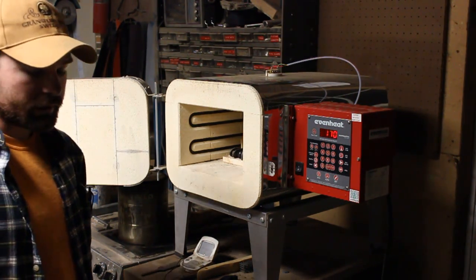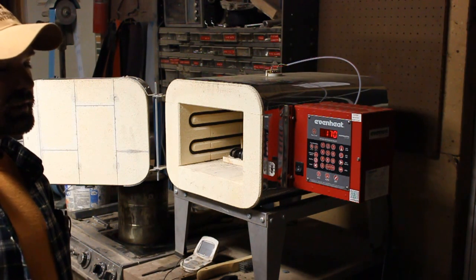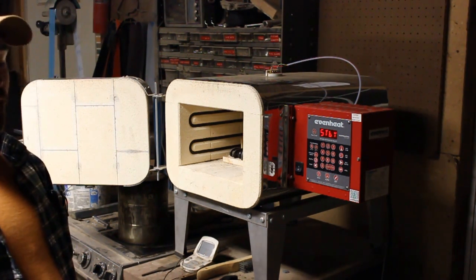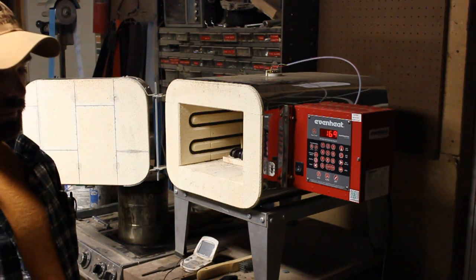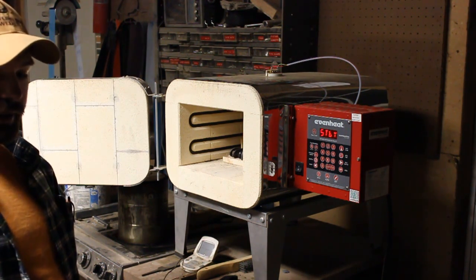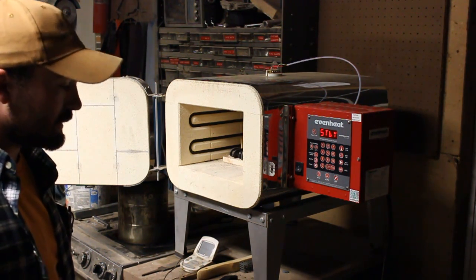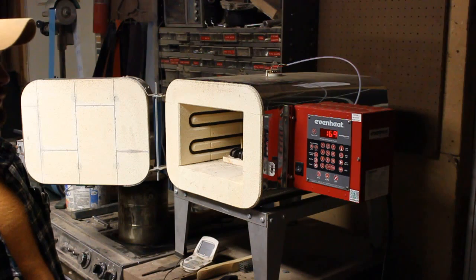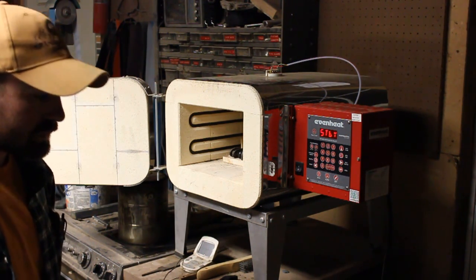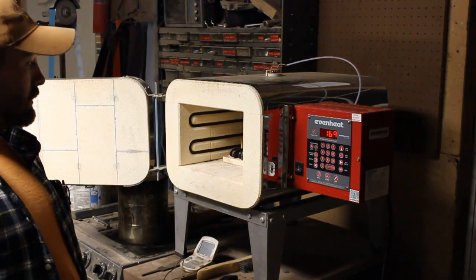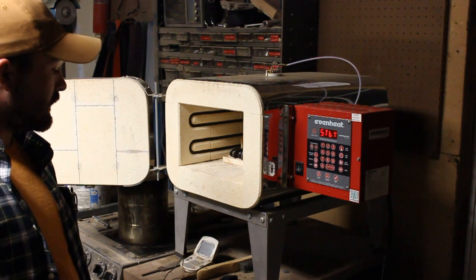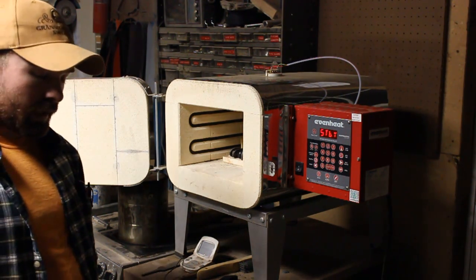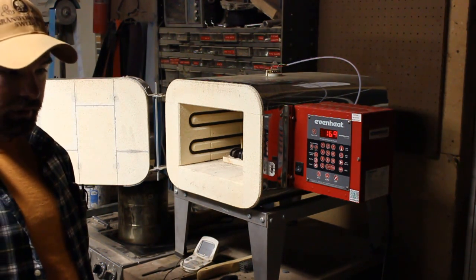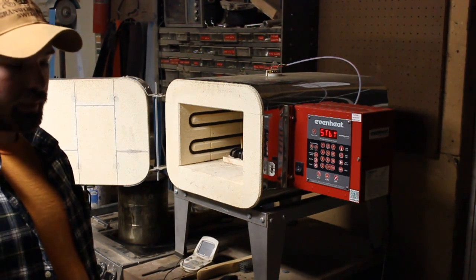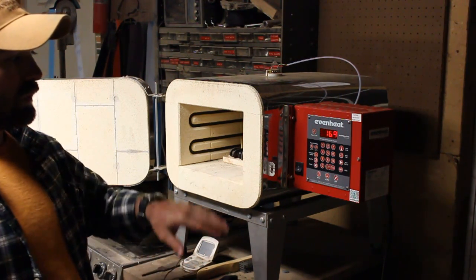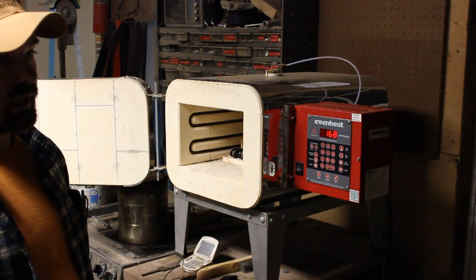So I shoot for 60-61 Rockwell on the C scale. I do not have a Rockwell tester. It is recommended that you Rockwell test your knives, but I do not Rockwell test my knives. But assuming that you do everything correctly by the tables, that's the Rockwell hardness that you should attain. And I use a triple tempering cycle, or I triple temper my blades, not to be confused with one cycle that actually does that.